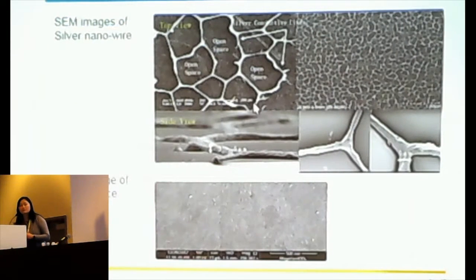So in our case, we try to provide a solution at a material level, and in this case, we can potentially make a device with certain curvature that is still touch sense capable. The material that we use here is a silver nanowire. It can self-assemble into a random structure. And because it's a silver nanowire, it can be flexible. It will not really break as compared to the ITO paste. The ITO paste, at similar dimension, is very stiff, actually.